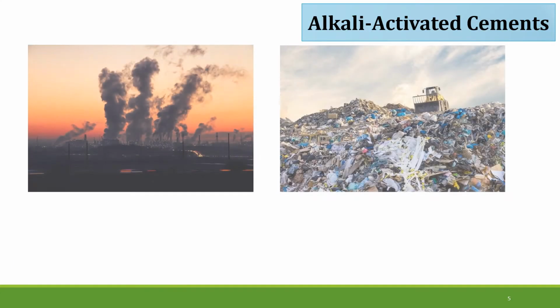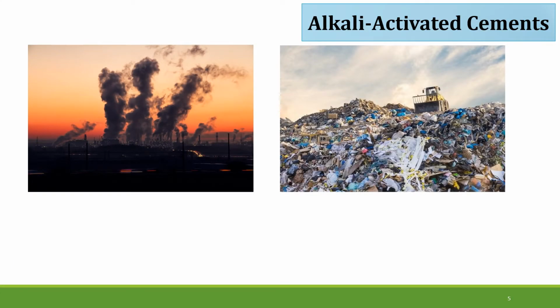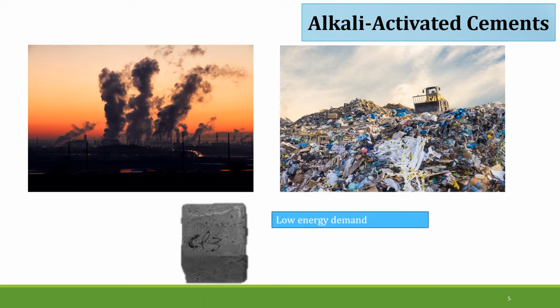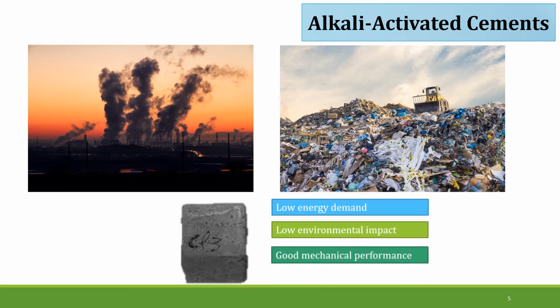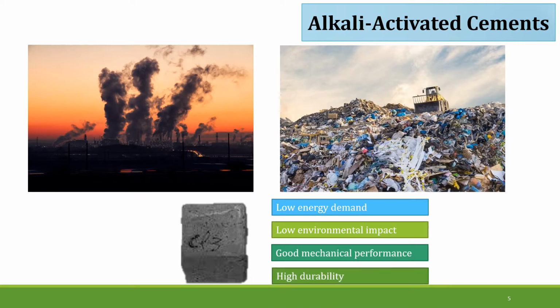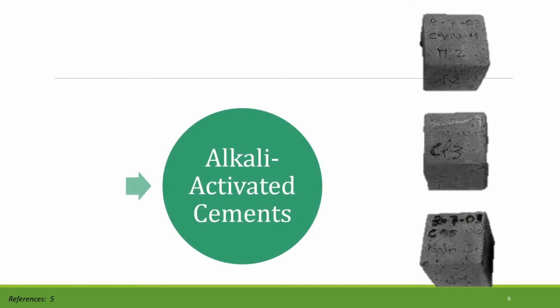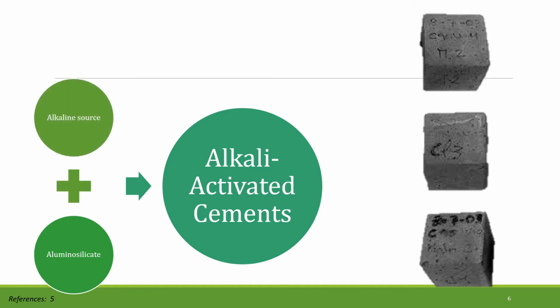In order to reduce pollutant and solid waste emissions, alkali-activated cements have been considered as a viable alternative due to their lower energy demand and environmental impact, with good mechanical performance and durability. These materials are obtained from the combination of an aluminosilicate such as metallurgical slag, fly ash, or silica fume, with an alkaline source called activator. The mixture of sodium hydroxide with sodium silicate is the most widely used activator.